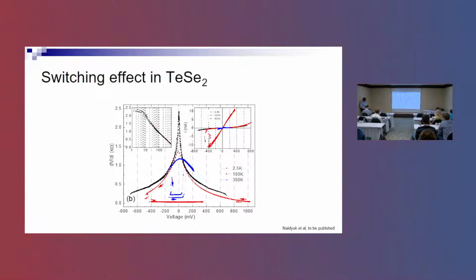But in addition, what was found is quite interesting. Here is the resistance, the first derivative of the voltage over I. If we apply this voltage, it's a metallic state with quite small resistance. The resistance of this point contact is about 10 ohm, and it depends on how you prepare the contact. This is a little bit of an uncontrollable process, but nevertheless, if you do statistics over 100 different point contacts, you can get the following. If you apply the voltage, it's reversible: if you increase the voltage, you have an increase of the resistivity.